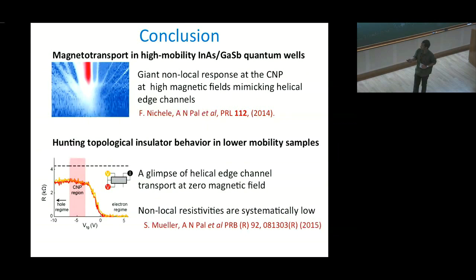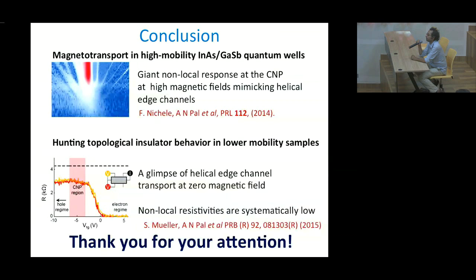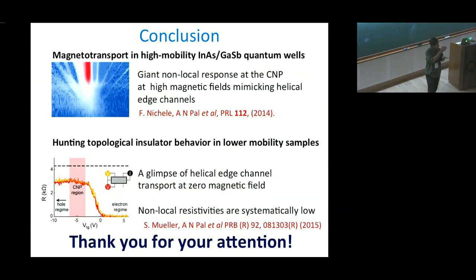We have rotated the magnetic field and also applied a parallel magnetic field. In parallel magnetic field, the band structure changes — there is a semiconductor-to-semimetallic transition in this material. We observe that the resistance peak decreases and it shows semimetallic-like features.